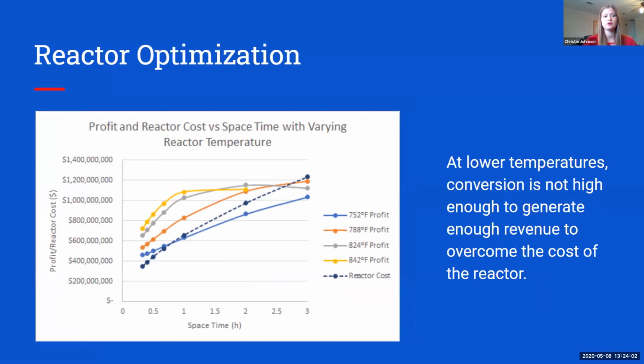And now on this slide, you can see that trade-off between space-time and reactor volume. Since the reactor made up such a large portion of the FCI, the FCI would increase greatly whenever you increase the residence time of the reactor by making it larger. So at those lower temperatures, you're not able to make a profit because the reactor cost is so expensive that it outweighs the revenue that you could be making at higher temperatures.